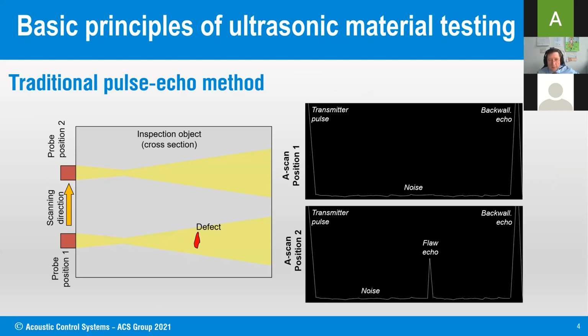As I have told, ultrasonic testing is a very widely used technique. If I try to exemplify the idea of UT with this page, the main technique used for UT is the so-called pulse echo, where from one insonification surface we apply a transducer and we get echo signals. Very simplified, if we have no defects inside of the material, we can only see the reflection from the back wall echo. And if there is a defect inside, we'll see some flaw defect echo, and the estimation of the size is, according to the state of the art, based on the amplitude information.